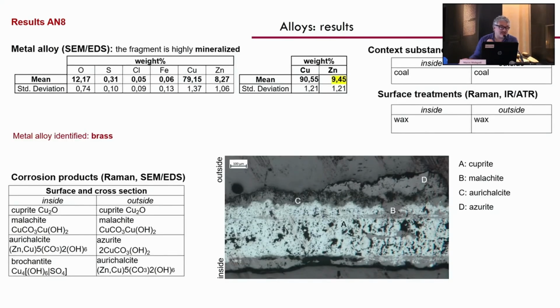Another brass, in this case totally mineralized, with a lower concentration of zinc, with all the oxidation phases of the degradation process that you can see. And even in this case, the wax was the organic material.